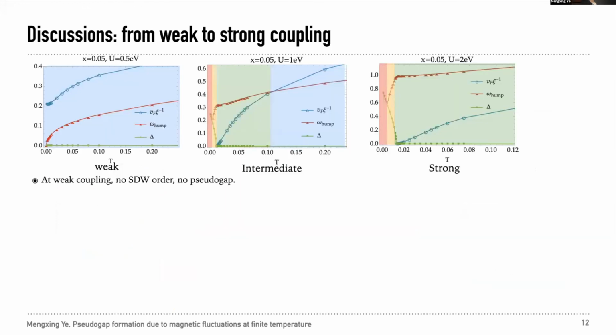And let me next say how these 3 energies change as we vary the coupling, the Hubbard U. For weak coupling, we don't see any SDW order and also no pseudo gap. From intermediate to stronger coupling, we see qualitatively the same thing. The only difference is the pseudo gap region becomes broader as we increase the Hubbard U.